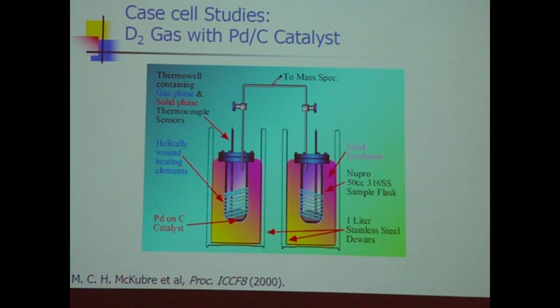Now, one of the first experiments that's relevant to this is an experiment that was originally pioneered by Les Case, who is sadly no longer with us. Les Case had a catalyst, a small amount of palladium on a carbon-based catalyst. You load it with deuterium at elevated temperature, and Case saw prodigious amounts of excess heat. And Case sent his gas to be analyzed, and his gas showed more than 100 ppm of helium-4.